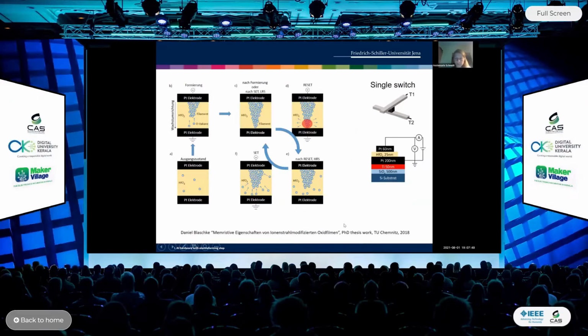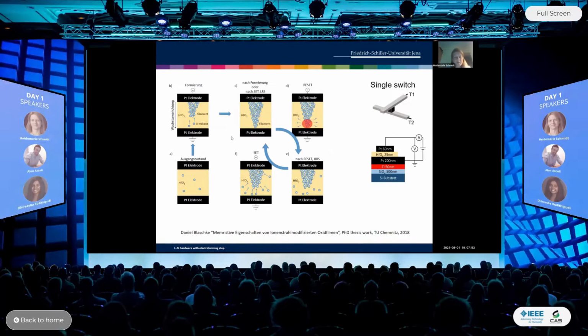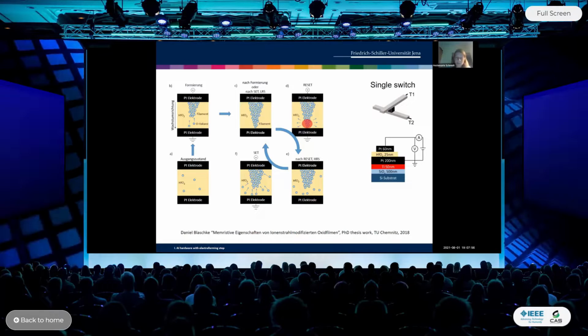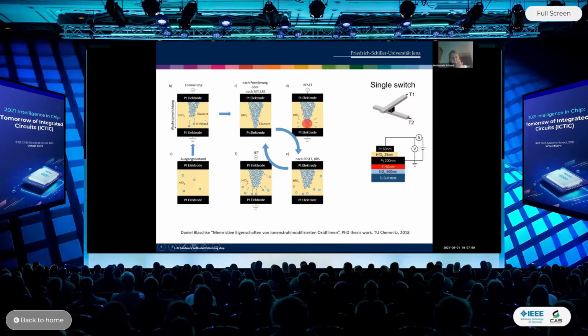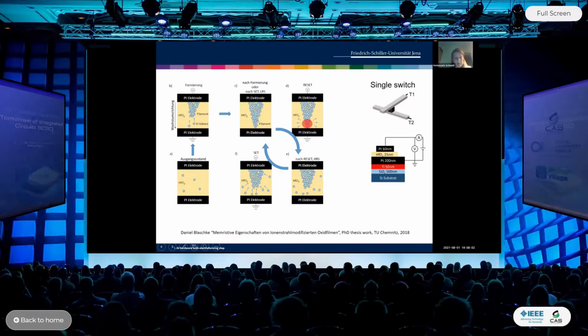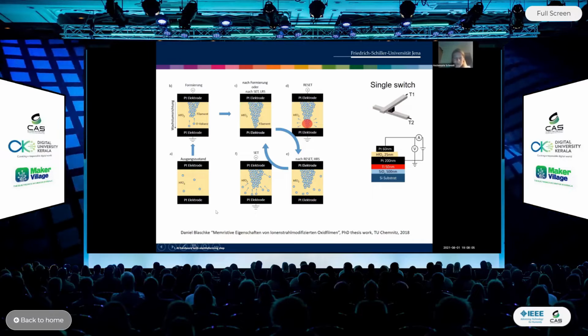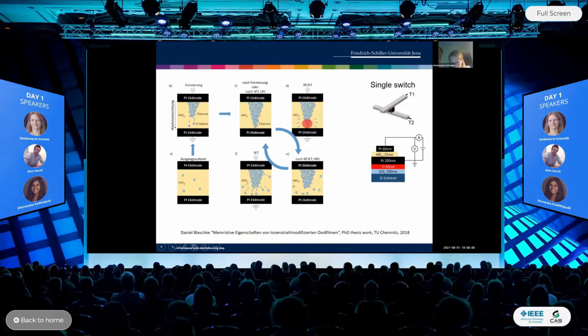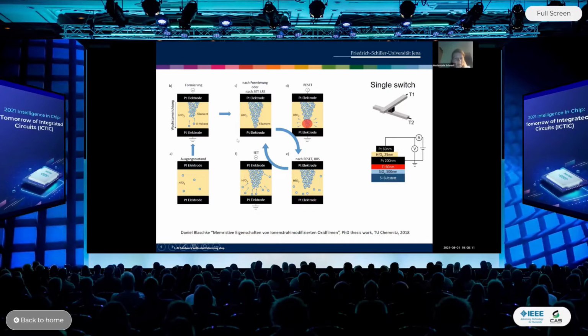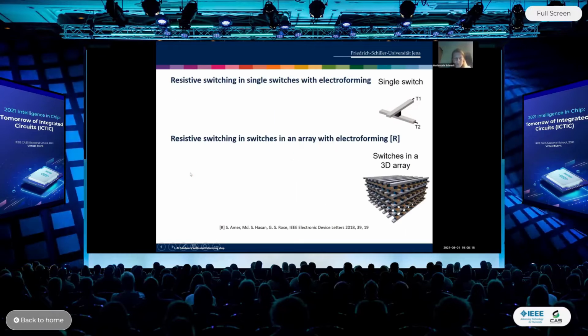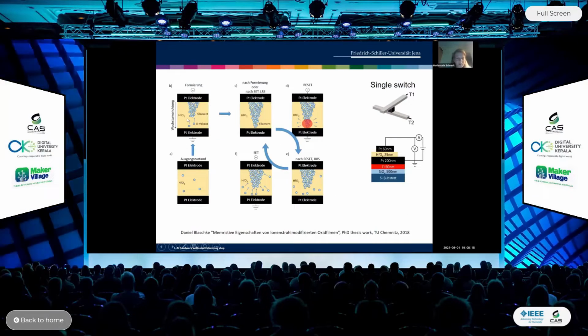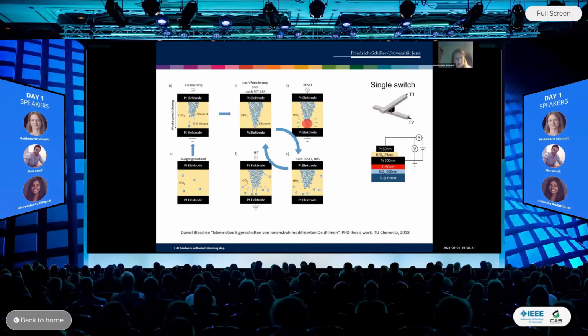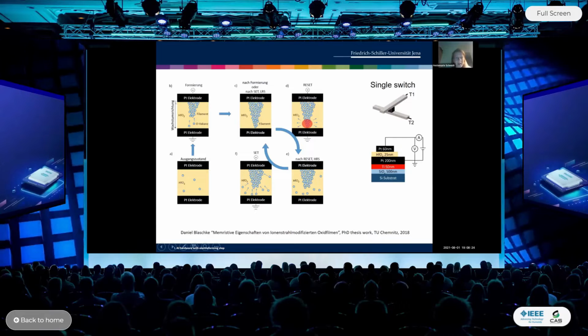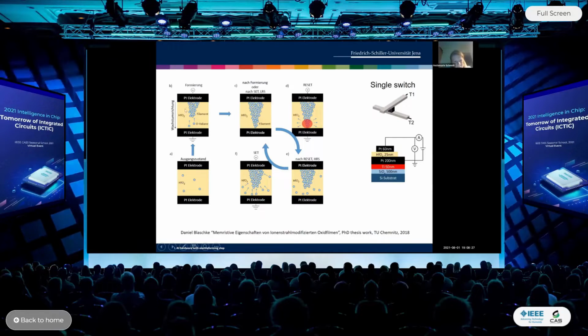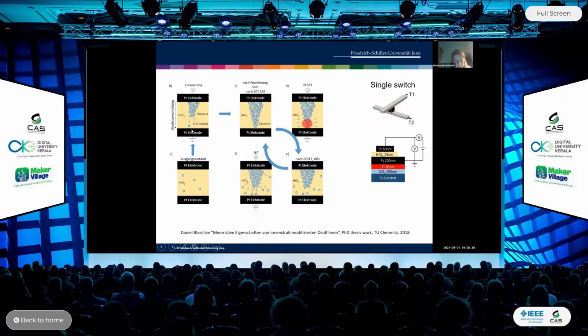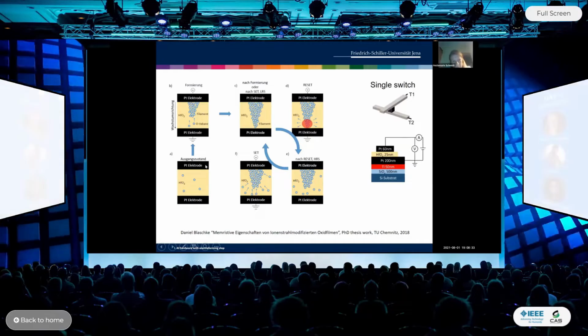The well-known explanation for such an electroforming step is the formation of filaments. I could imagine that maybe you already heard about how electroforming is explained. So let's take the special case of a hafnium oxide memristor. This is the hafnium oxide here between the top electrode and the bottom electrode. And what you see is a schematic sketch which explains the formation of filaments, and which explains why you need in the beginning at least once a large bias. So you need this large bias to form this filament between the top and the bottom electrode. And then this is the electroforming step.